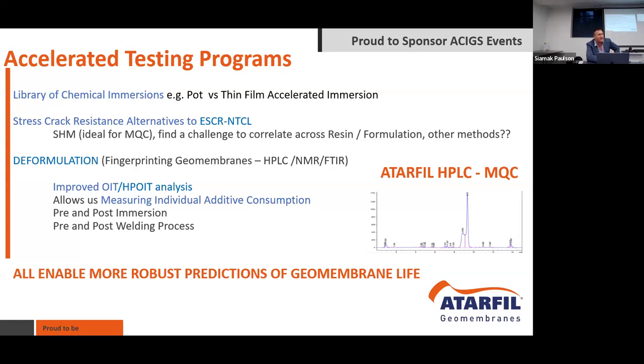Work we've been doing heavily is deformulating, essentially fingerprinting these geomembranes. Rather than doing block OIT and HPOIT loss, we're looking at specific reaction rate loss of specific additives in the actual polyethylene. It can give you really robust measures of project predictions, particularly if you do it pre and post long-term immersion. You get a great sense of what's driving performance of the liner over time. We also do it pre and post welding, because you're welding at 400 degrees and you want to know what additives are being consumed at those temperatures. All of these enable more robust predictions of geomembrane life, and it's the Atarfil ethos.